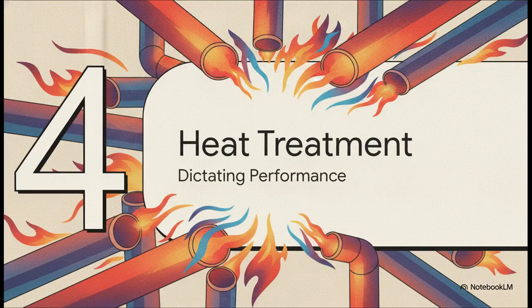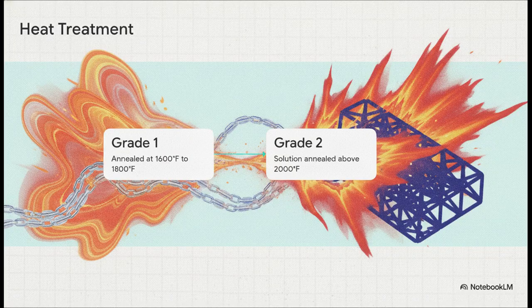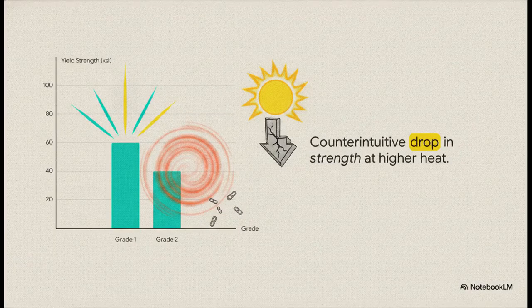Section 4. Heat treatment and performance. The stark difference in performance between these two grades is a direct result of their heat treatment. During manufacturing, Grade 1 is typically annealed at a temperature somewhere between 1600 and 1800 degrees Fahrenheit. This gives it excellent ductility and corrosion resistance. Grade 2, on the other hand, is solution annealed at a much higher temperature, specifically above 2000 degrees Fahrenheit. And pushing the heat treatment past 2000 degrees doesn't just warm it up, it fundamentally reorganizes the internal atomic and metallurgical lattice of the whole alloy. It's like rearranging a giant puzzle. Now, what's really interesting about this is that the extreme heat treatment produces a highly counterintuitive result.